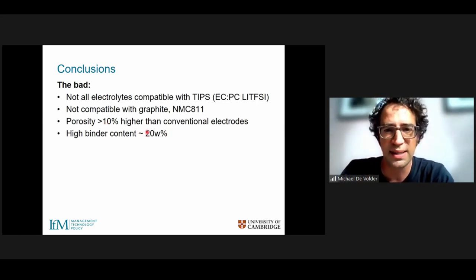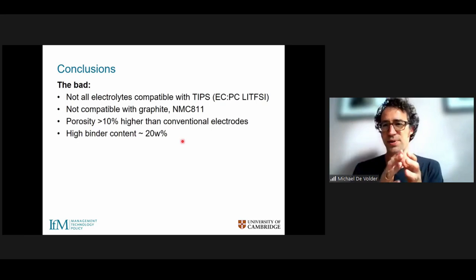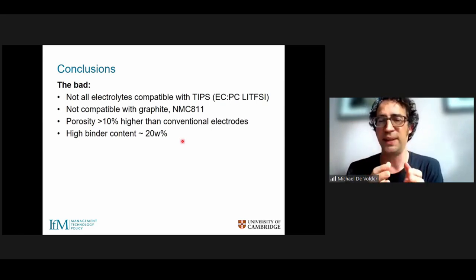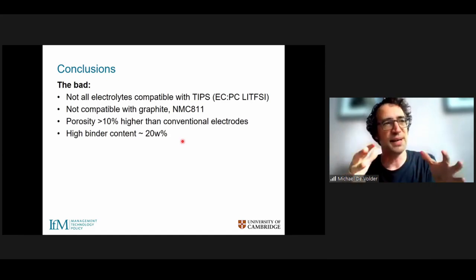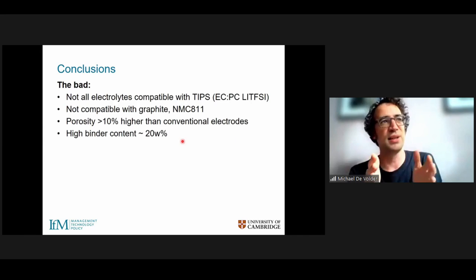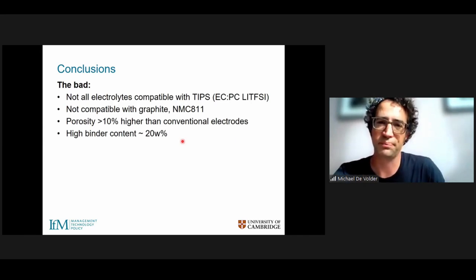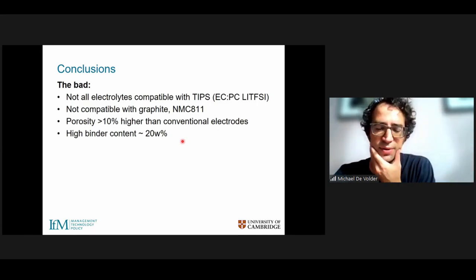And then finally, a disadvantage I wanted to highlight is that for the TIPS process to take place, you need to add quite a lot of this PVDF, because the PVDF, the binder, is what drives the phase segregation. If you don't have enough of it, it will not be able to control the bicontinuous electrode formation process.